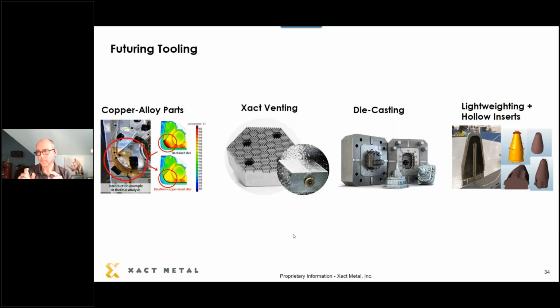But I want to point out that by thinking about things differently, I took what was a conformal cooled insert that took 197 hours to print at a price just under $5,000, and got it down to about a 92-hour print by printing it hollow. The thought was, I went to the guys over at Inspire Software and said, if I've got 18,000 PSI of plastic pressure on here, how thick does the wall really need to be? Do I really need a solid chunk? Turns out you don't. I needed 4 mils of wall stock, really? So I went 5 mils of wall stock because, belts and suspenders, why not? Go a little bit thicker because that's what we do.